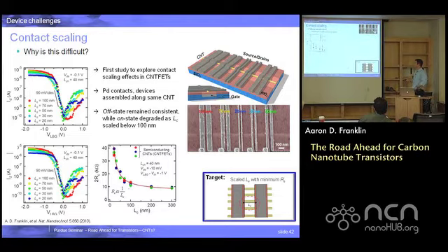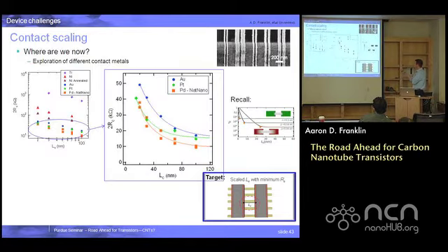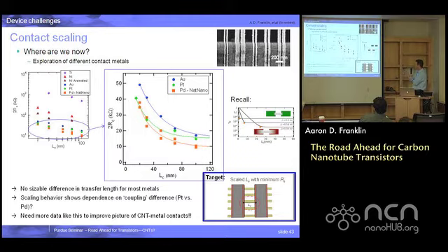One of the things that we've done most recently, I'm missing actually, we have a couple more curves on here that are interesting, but we're looking at how different contact metals scale compared to palladium. So the orange scaling trend is the one that I showed on the previous slide. Our other work we've been doing now is looking at different metals and different interfacial layers and how it affects what the scaling behavior looks like. Because what I want more than anything is to get some devices down here in the lower resistance and small contact length area. And that requires changing this type of scaling behavior. So there's a lot of work that remains to be done in this particular area, where a lot of material science, good work with interfaces could play a big role.